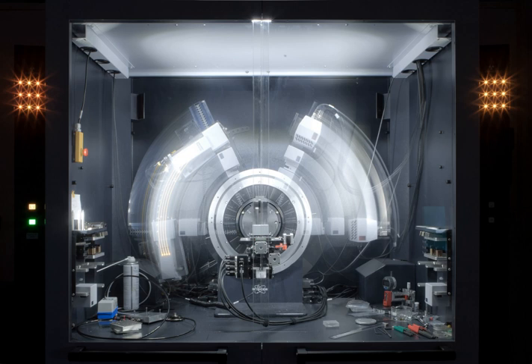A full 360 degree rotation is not needed because of a symmetry intrinsic to the Fourier transforms of real functions, such as the electron density, but slightly more than 180 degrees is needed to cover all of reciprocal space within a given resolution because of the curvature of the Ewald sphere. In practice, the crystal is rocked by a small amount, 0.25 to 1 degree, to incorporate reflections near the boundaries of the spherical Ewald shells.